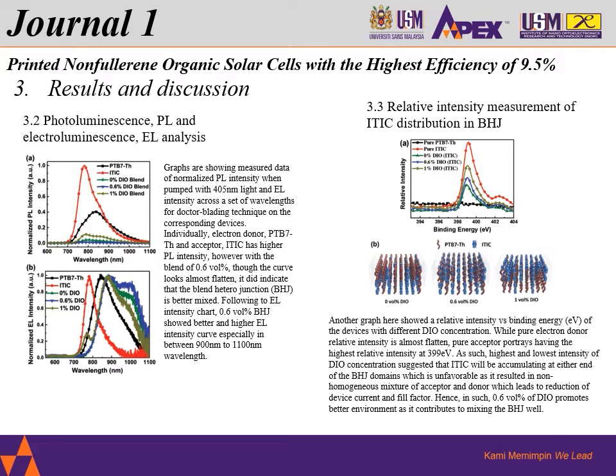So in short, what we are seeing over here is the individual, or the pure ITIC, which is the acceptor, has the highest photoluminescent intensity, and then followed by the donor. However, with the blend itself, we can see a flat graph, especially on the reported 0.6%, which has the maximum PCE, and this actually indicates that the blend heterojunction is well mixed.